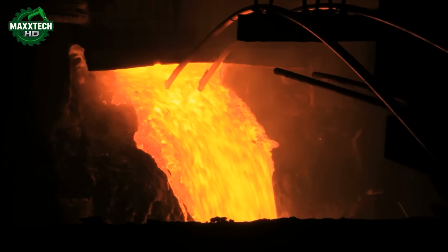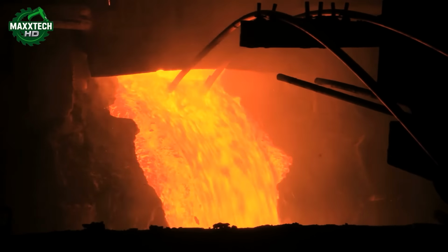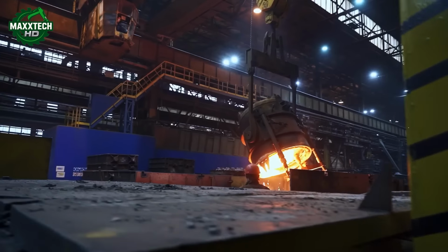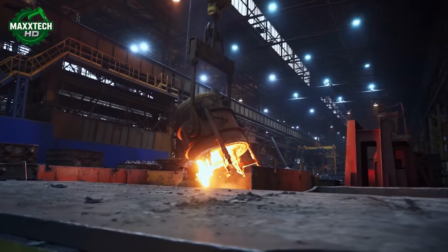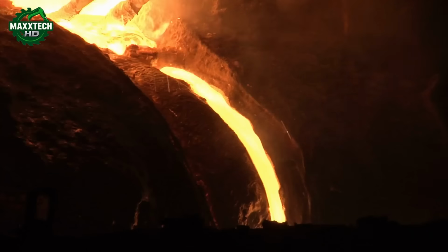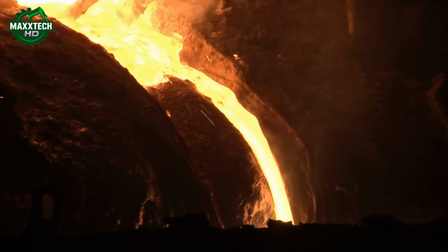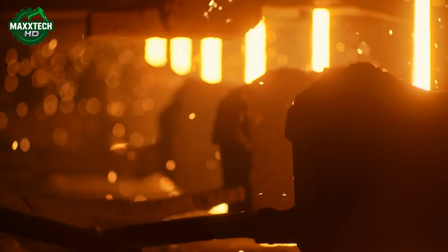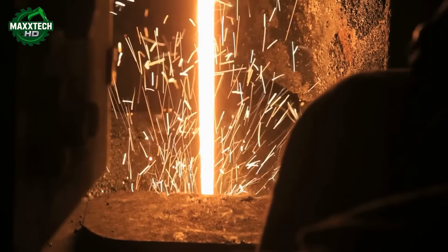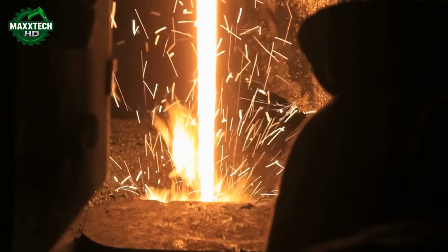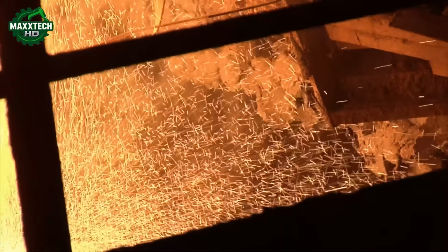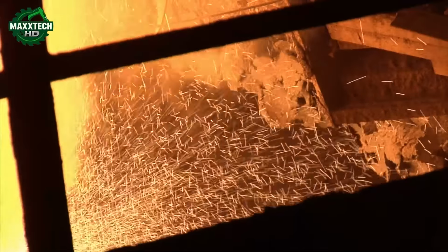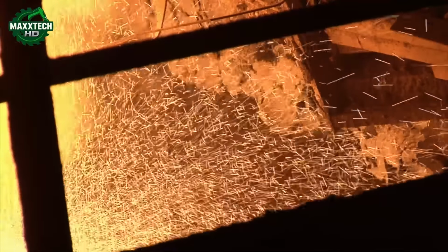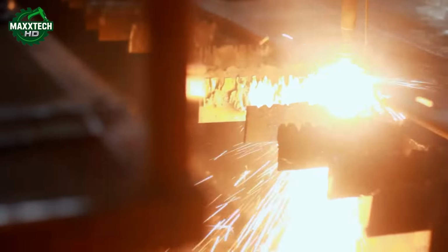After 2.5 noisy hours, the liquid metal is ready, and the ladle crew takes over. Using a manned crane, they guide a 9-ton ladle to the furnace and pour out a fiery river of metal, hotter than a volcano. Then comes the trickiest part: guiding the molten metal into the mold shaped exactly like the final frame piece. The metal flows in with a flash, and the mold must cool for 36 hours before the casting emerges.